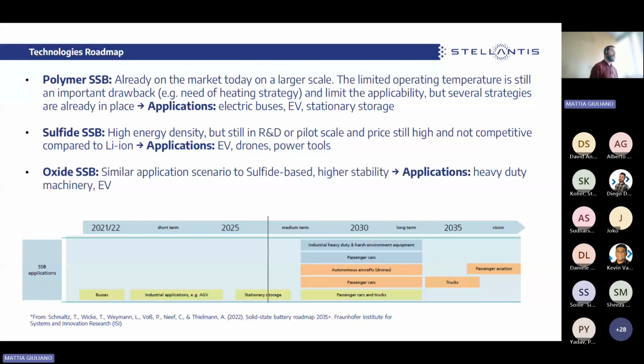Looking into the possible usability scenarios, polymer solid-state batteries are already in the market, also on a quite large scale. They are still limited in terms of operating temperature, and it is an important drawback. But several strategies are already in place, and this technology, from the automotive point of view, is already applied on electric buses, but also in some electric vehicle applications. Sulfide-based is probably the most interesting chemistry for mobility, due to the high energy density and also the good conductivity. But it's still at R&D scale or pilot scale, depending on the technology, and the price is still high and not competitive with lithium-ion. So probably the first usability scenario will be mobility, but these bottlenecks have to be overcome.